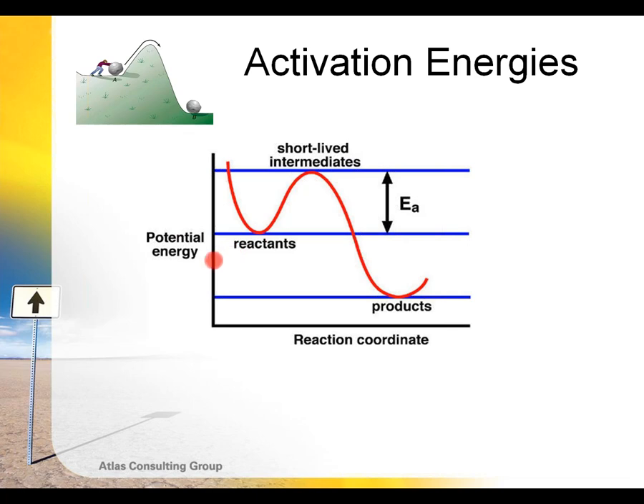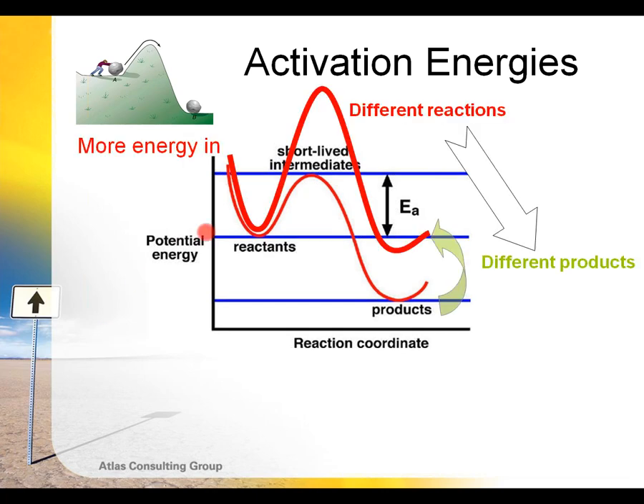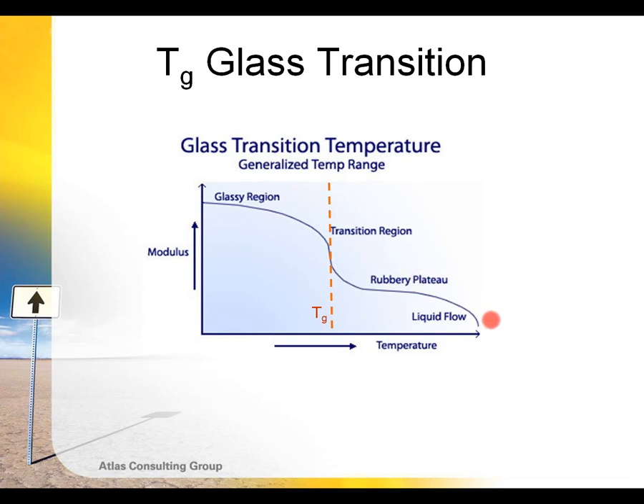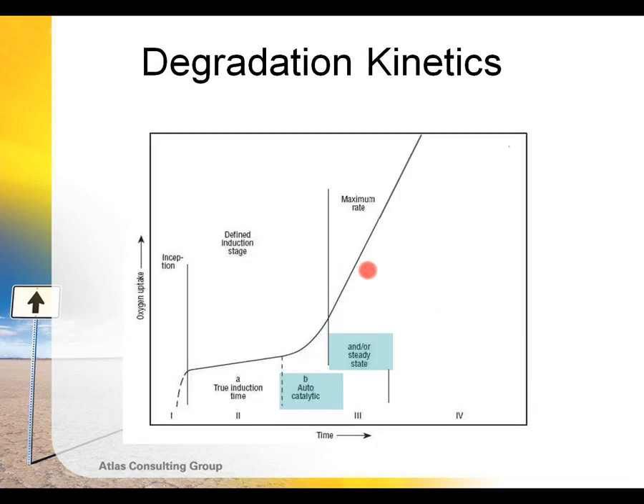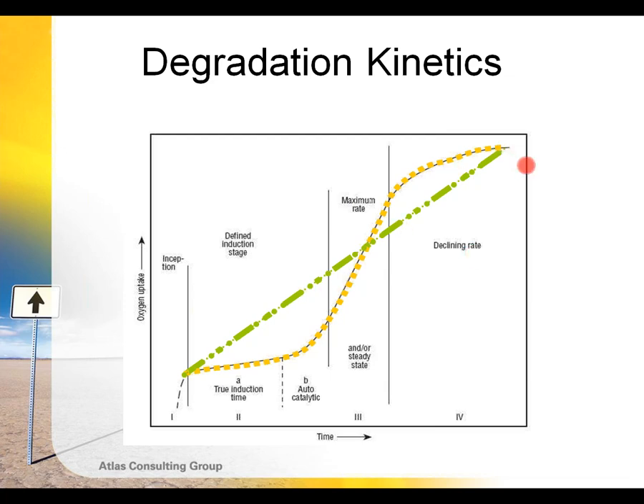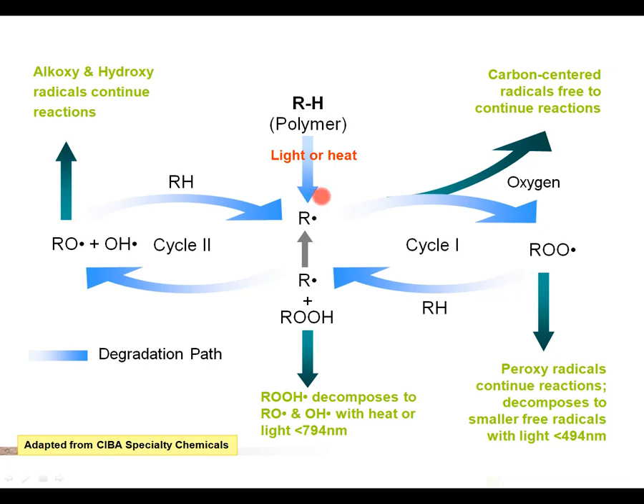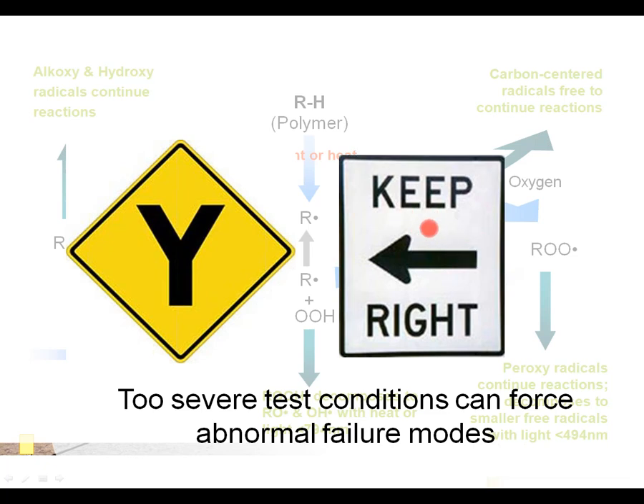There are many chemical reasons why products behave in a nonlinear fashion. I'm not going to try to discuss those, but they have to do with activation energies of the product in relation to the test, and fundamental properties such as polymer glass transition temperature versus test conditions. The degradation kinetics typically undergoes a classic S-shaped curve, and you need to understand where you are on that curve in terms of predicting long-term performance based on short-term tests. There can also be fundamental changes in the chemistry. I can drive and force a different chemistry to occur by choosing inappropriate conditions of the test. So my little road sign here: we can force a product to take a path it would not normally take just by changing the conditions of the test.